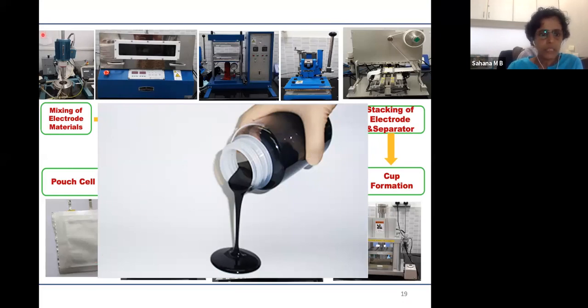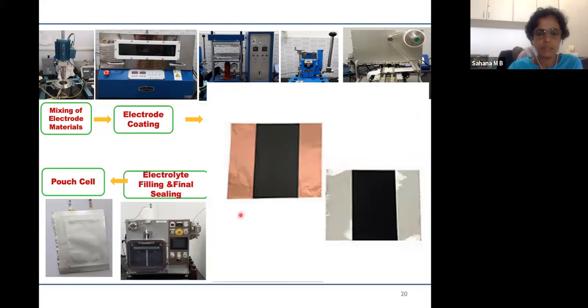Now, the first thing is mixing of the active materials with the conductive additives like carbon black and binder. So we get what is called a slurry, which you can flow very easily. But it should not flow too easily, so that the active material or the carbon black does not sediment. The slurry property plays a very crucial role in determining the quality of the electrode. After that, we coat this slurry on a current collector and dry it.